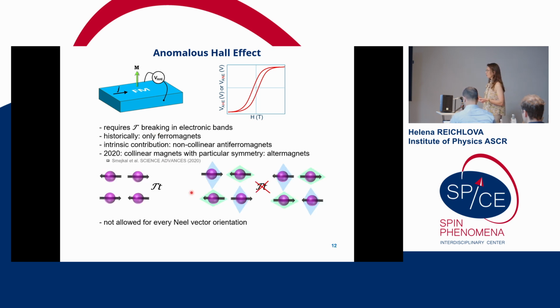What is important to note is that in conventional collinear antiferromagnets, the time-reversal symmetry T is a symmetry, as when you flip the spin and translate it by a half unit cell, we recover the picture. But when we now consider also this anisotropic non-magnetic environment, we cannot do the same exercise by flipping the spin, and we cannot translate it by any half unit cell to recover the original image.